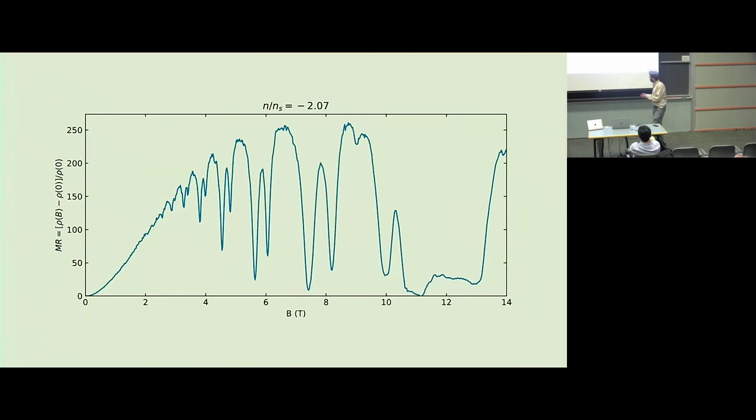Now let's do a cut in magnetic field within one of these magnetoresistance regions. Again, there's strong magnetoresistance, and then we start to get oscillations. The magnetoresistance is quite close to quadratic. The oscillations are a little unusual. Where we would expect a Landau level, we see a doubling, two dips that are split off from the expected location.